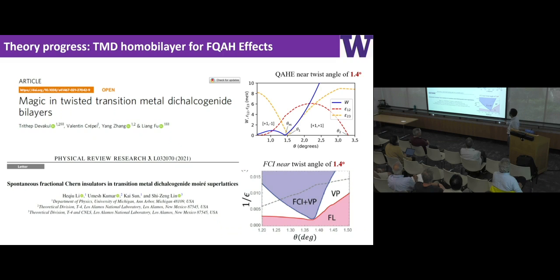They studied twisted WSe2, and it shows that there's a quantum anomalous Hall effect at a twist angle of about 1.4 degrees, and also with an indication of this FQAH state. And the other one is more relevant, from the collaboration between Kai Sun and Shi-Zheng Liu. What they show is that in MoTe2 systems, they did this many-body calculation. They found this Chern number. Basically, you can have this fractional Chern insulator state near a twist angle of 1.4 degrees as well, just consistent